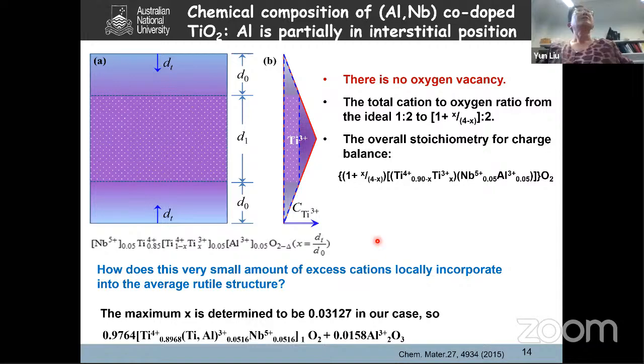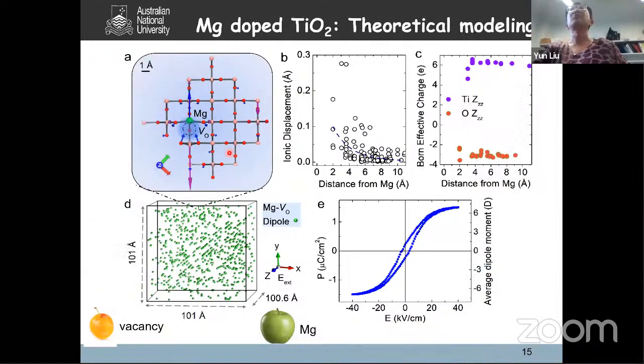Such difficult to dope ions also don't have to have a second extrinsic ion to create the environment and to accommodate them. You can also push the local structure environment, for example, push oxygen away, so this kind of difficult to dope ion will form the defect cluster with the oxygen vacancy. Okay, because magnesium is a difficult to dope ion, these permanent dipoles will significantly affect the surrounding chemical environment.